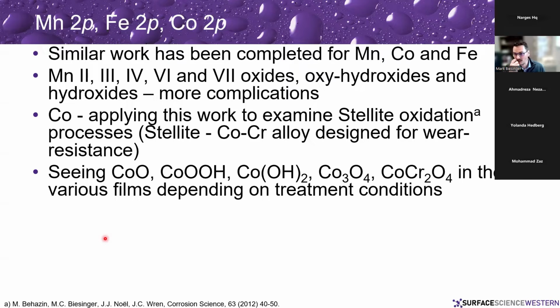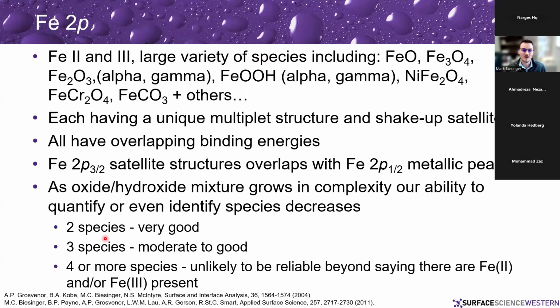Cobalt's the same. Again, lots of different possibilities of different cobalt oxides, mixed oxide hydroxides, and then of course sulfides and phosphates, et cetera, et cetera. One of the systems we looked at a lot was a stellite system, which is a cobalt chrome alloy. So there's mixed oxides there, cobalt and chrome alloys, and you have to model all those things in. So you're not just pulling out, okay, I have cobalt 2 or cobalt 3. It doesn't work that way. You've got to pull out what species you actually have for the most part to really understand what's going on in your systems.